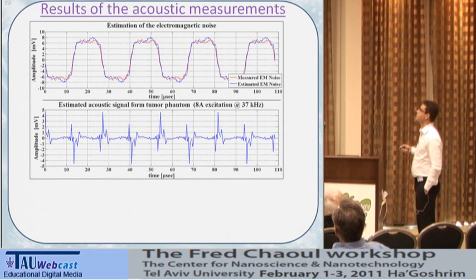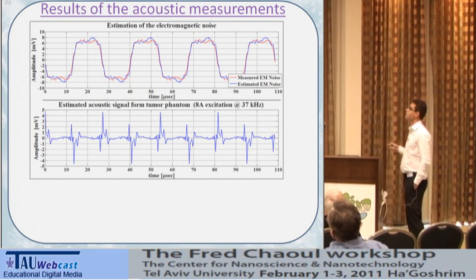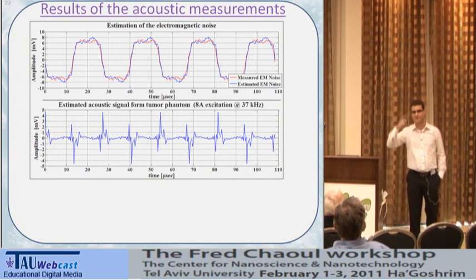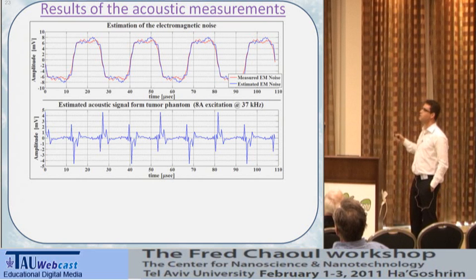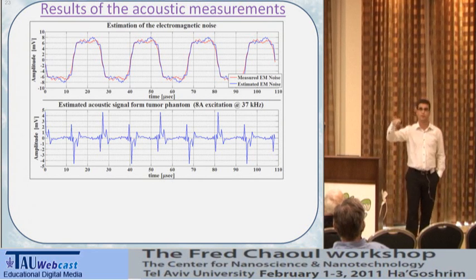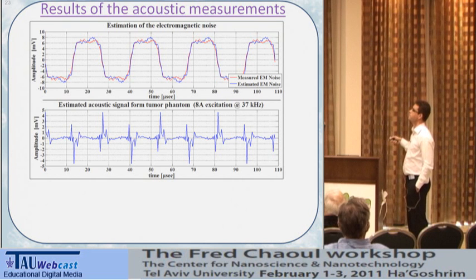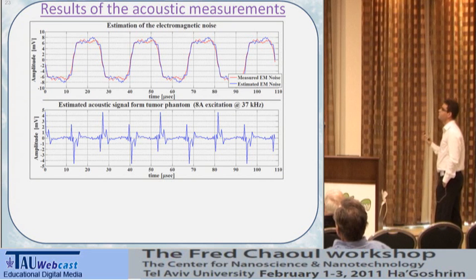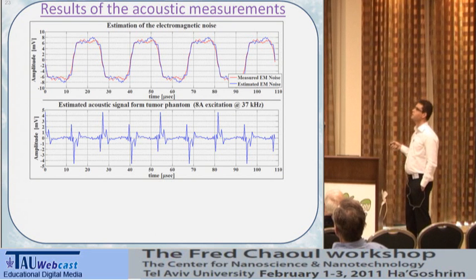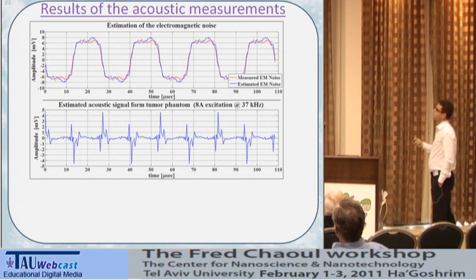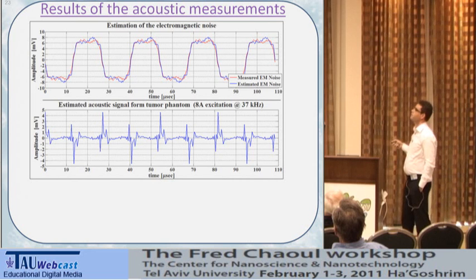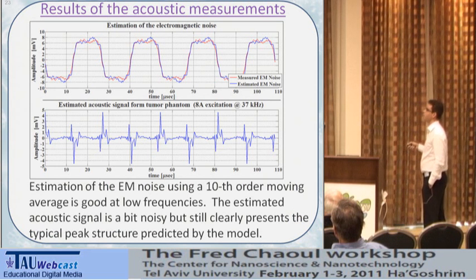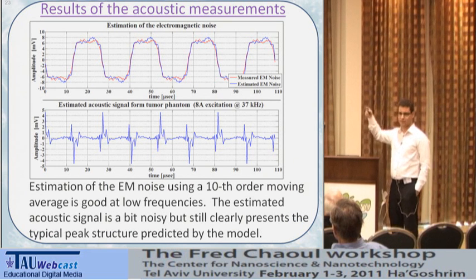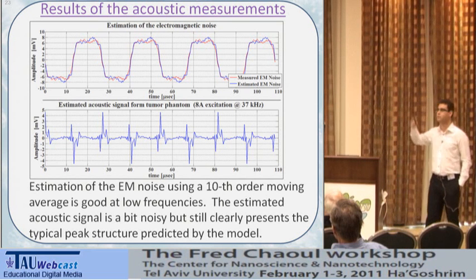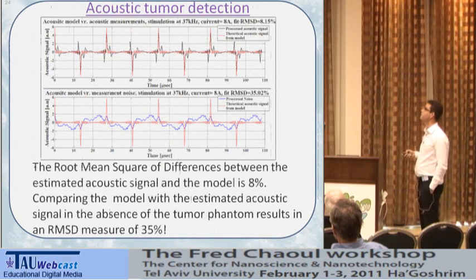And what we got was basically this, which looks much like our excitation noise. It's an electromagnetic noise. We excite the solenoids with a square wave, and as you can see, what you measure in the sensor is also a square wave. But if you do the signal processing and subtract the square wave excitation from this pattern, what you get is this, which looks very much like our model, if you remember: the series of inverted spikes corresponding to the pushing and pulling of the nanoparticles. So we did this, and then